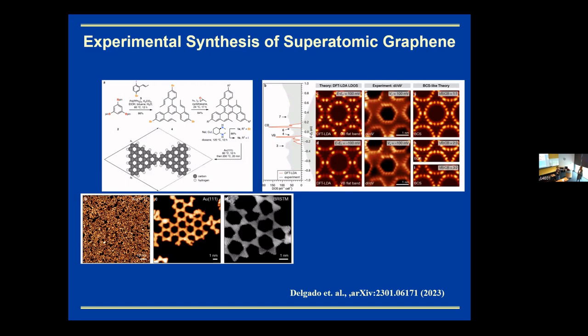But you can have a 3D flat band, where the flat band in the whole 3D Brillouin zone has a constant energy. That's possible. There is a material called pyrochlore or something similar. They have a three-dimensional flat band. Pyrochlore is a direct analog of the Kagome lattice in 3D, so they can have a 3D flat band. So you can also construct a 3D line graph. In that sense, you can also construct the 3D BDC we just recently developed.